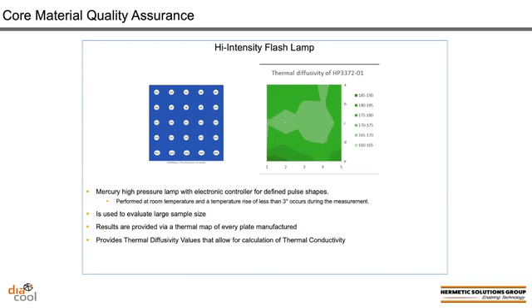So one of the tests that we use to help us engineer and evaluate this material is the use of this high-intensity flash lamp. You can see here in this blue image on the left-hand side of this slide, this is essentially a fixture that has these high-intensity flash lamps distributed across the surface of that fixture. And in this case, we take these substrates of Diacool and place them into this flash lamp and flash the material and take a thermal image that tells us the thermal diffusivity of the material depicted here on the right-hand side in this green image.